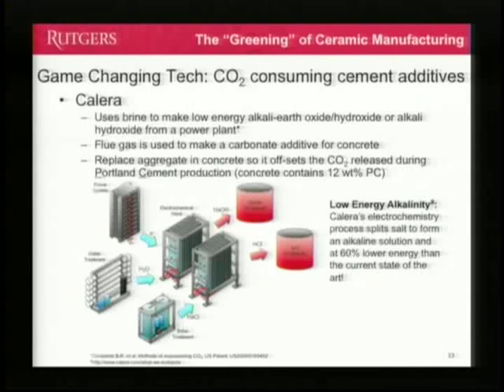The other thing they're doing that's nice, though, is they're using brine from reverse osmosis for their source of cations. And then ultimately, they're making this carbonate salt, which is the additive for concrete. So this is another way to kind of get around being green by finding some way of replacing something that can make the whole process appear carbon negative. Because you're storing the carbon in the process of doing this.